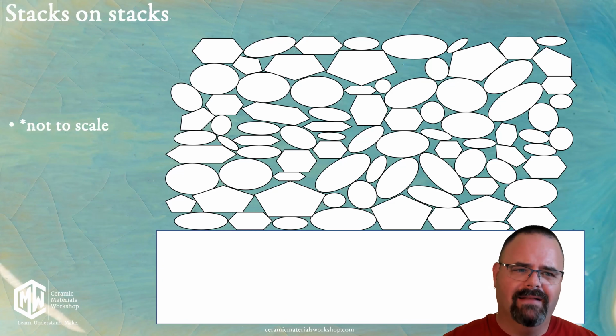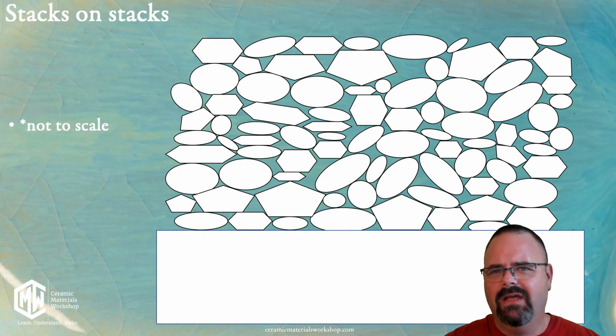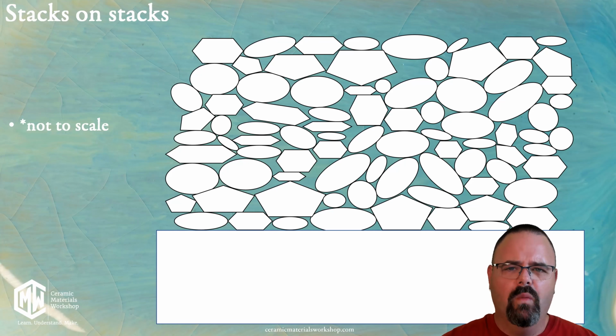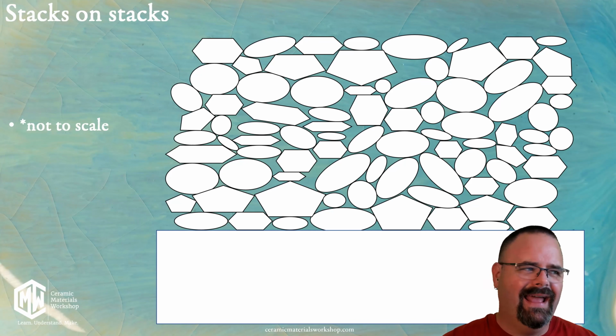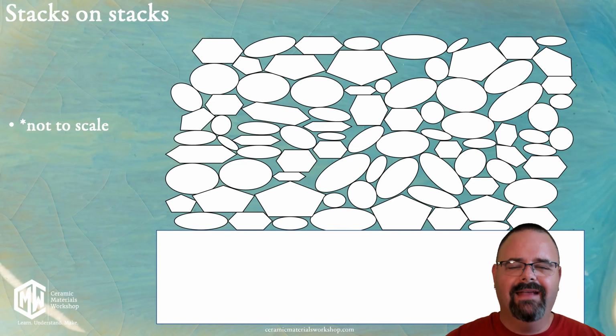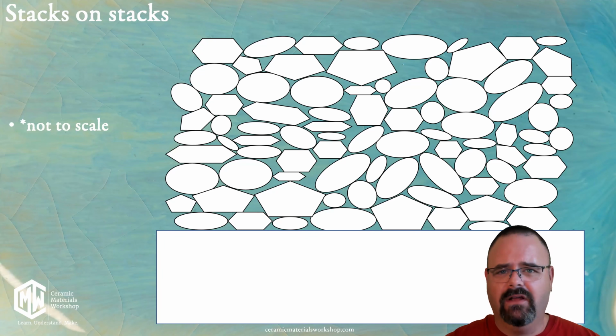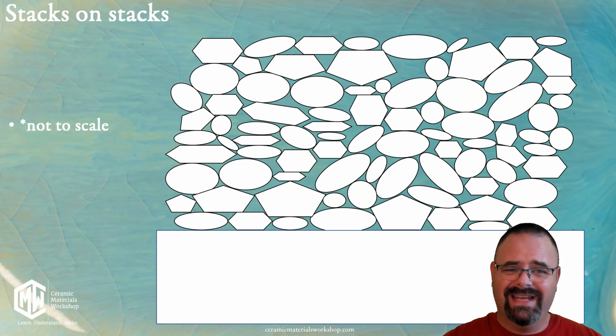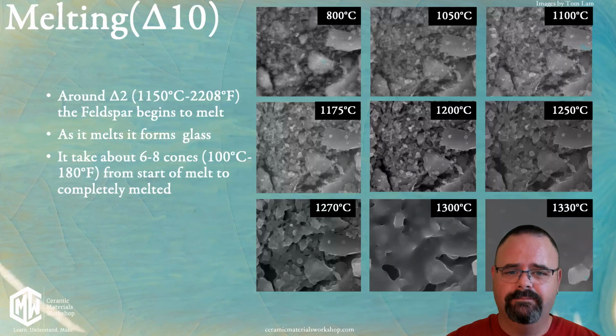You see, when we apply glaze to a pot, we sort of see it as a liquid that becomes a slightly dry powder when we put it on the surface of our pot, but that's not actually giving us an accurate perspective on what is going on inside of our glaze, because a glaze applied to the surface of a pot is actually millions and millions and millions of tiny particles all packed together like this. You've got your clay particles and your feldspar particles and your silica particles and your whiting particles all packed there on the surface, and that's pretty much it, okay? But the more important detail is what happens when we melt them.